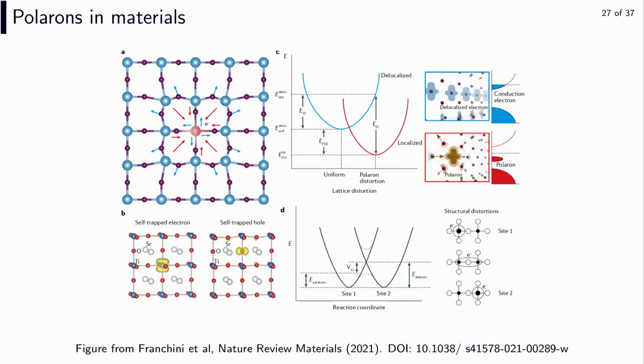is about. So I assume that everybody at some point in their life has heard about polarons. The intuitive notion is that you take an insulator, a material, you add an electron, and if the electron-phonon interaction is strong enough, the electron may drag some atoms around itself, and then these atoms will actually pin the electron at their location, forming essentially a Landau-Pekar-type charge, a combined electron plus atomic displacement unit, and this acts in a way that is quite different from standard electrons.